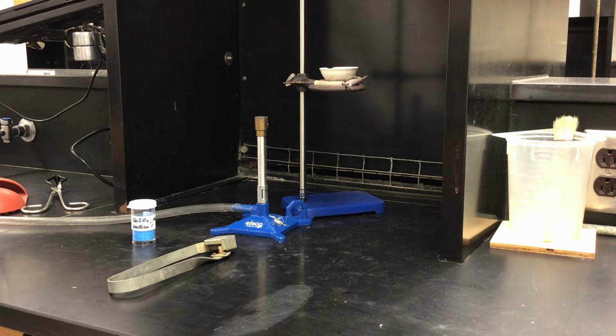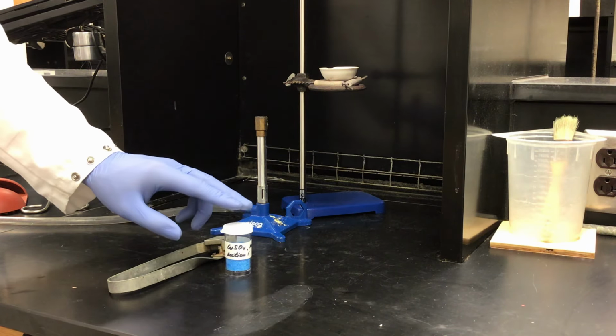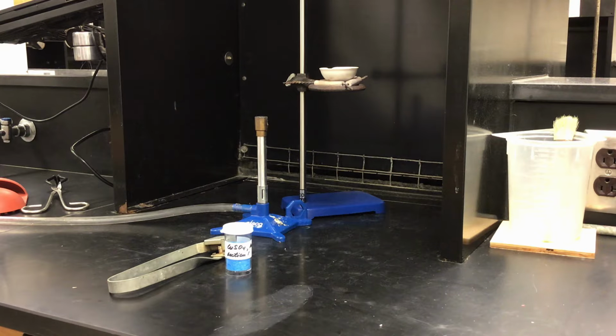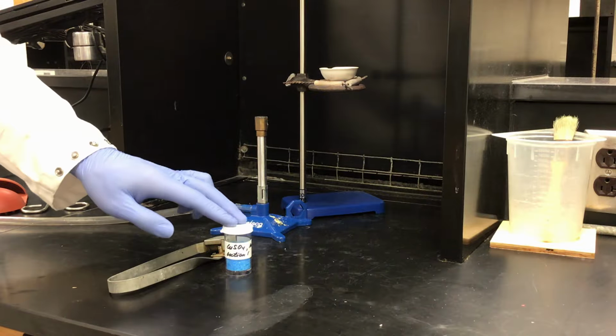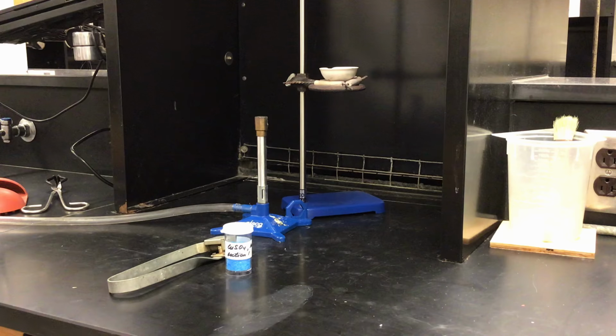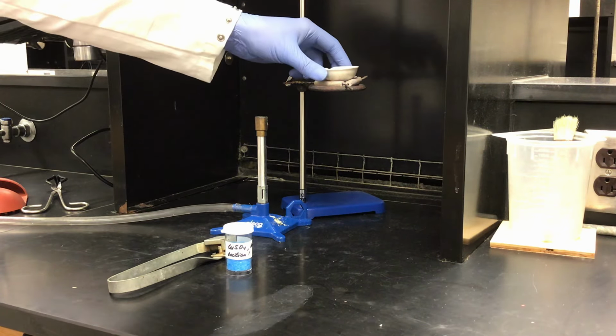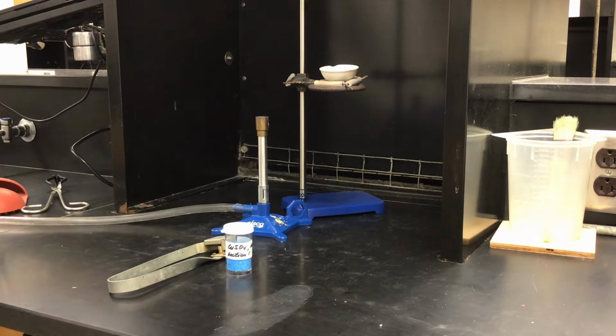Here we are moving on to our next part. I have here my copper sulfate, which we have now taken and found our percent yield, and we have found that we actually have a yield greater than 100%, which means we need to figure out what is going on. Since we should not be able to have a weight greater than 100%, we suspect that we have created a hydrated salt. Since we went ahead and very thoroughly dried it by vacuum filtration and letting it sit uncapped in atmosphere, this would mean that there is water of hydration inside the crystal complex. In order to find out if this is true, we are going to use an evaporating dish and our Bunsen burner to dehydrate our crystals and find if we have lost any water.